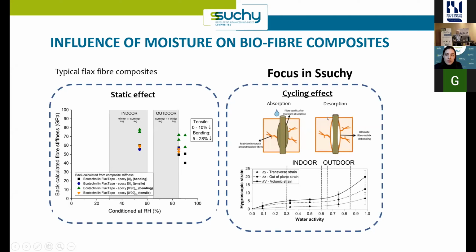But in the SUCHY project, we're mainly looking at the cyclic effect of moisture, where you create damage over time, because you get swelling of your fibers, you get shrinking again in lower humidity conditions, and all this swelling and shrinking can lead to potential damage. And that's the kind of thing we wanted to evaluate.